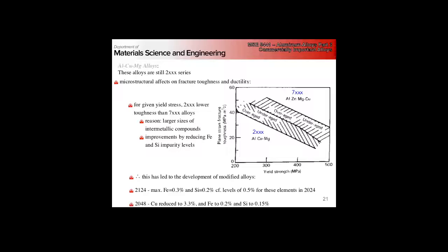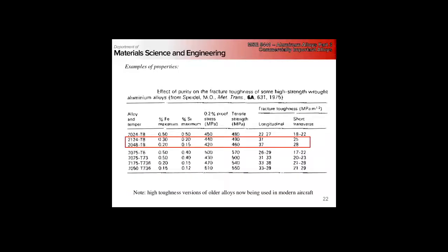2124, notice it's quite similar to 2024, so basically it tells you what it's related to. The iron and silicon are reduced quite substantially. And 2048, we are also quite lower. If we compare these to 2024, we see we've reduced the iron and silicon by about half.